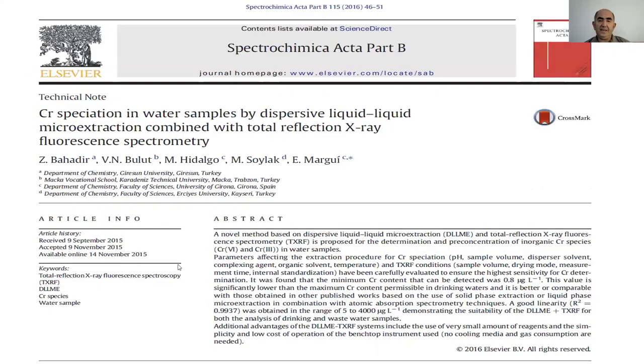But I can give an example about these kinds of works: chromium speciation in water samples by dispersive liquid-liquid microextraction combined with total reflection X-ray fluorescence spectrometry. We used carbon tetrachloride and chloroform as extractant solvents in this work, and we can get quantitative results for the speciation of chromium.